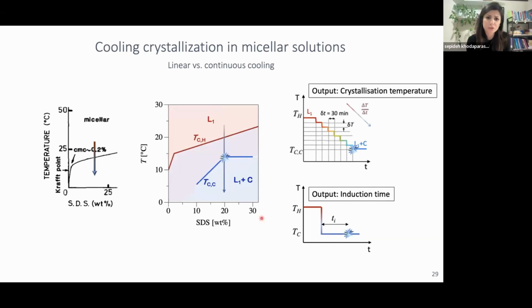Okay. So if you cool down the solution continuously, if you don't do this slowly enough, you might go below this crystallization temperature and never detect the crystallization. Similarly, if you go down the temperature and wait, if you don't wait enough, then you might miss that temperature. So every time someone reports this is the crystallization temperature or this is the evaporation temperature, you should be asking what technique they used and what algorithm, what protocol they used to change the temperature.